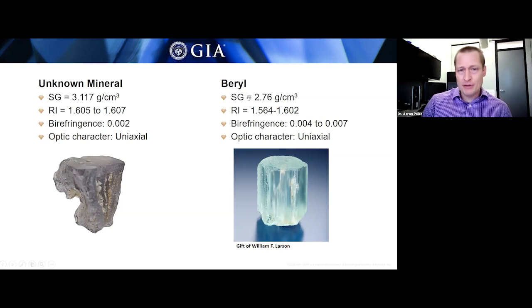The specific gravity was different. The refractive index was different, the birefringence was different. They both had this uniaxial optical character, but besides that, there wasn't a whole lot to really go on. So at this point, we took the stone outside of GIA, and we realized we needed to collaborate with colleagues from Caltech. So we were working with Chi Ma and George Rossman, as well as another fellow, Lawrence Henning, who is a single crystal X-ray diffractometer expert. And they all helped us kind of characterize this material a little more carefully.